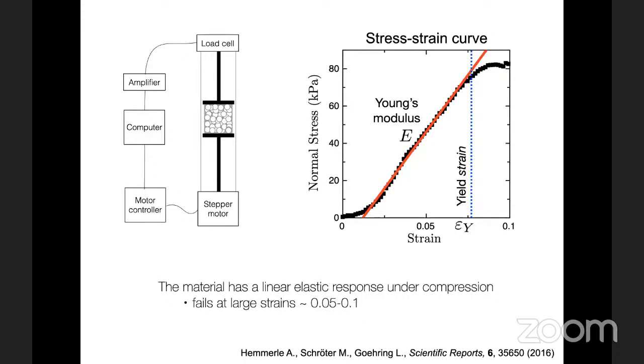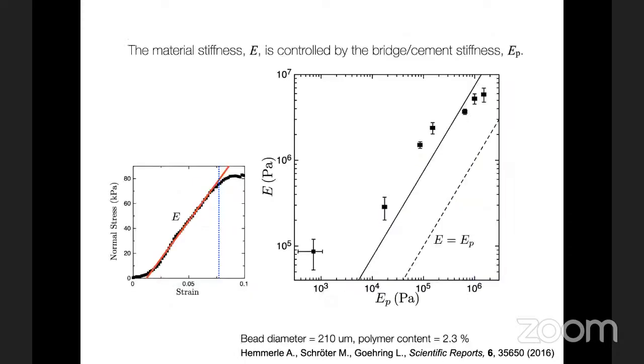The systems, as we made them in the lab, tend to fail by developing a shear band, so a brittle failure mode with a shear band at around that percent. We can then measure the Young's modulus. It looks like a linear elastic material for much of its compression until failure. And we can compare that Young's modulus to the modulus, for example, of the polymer that we add.